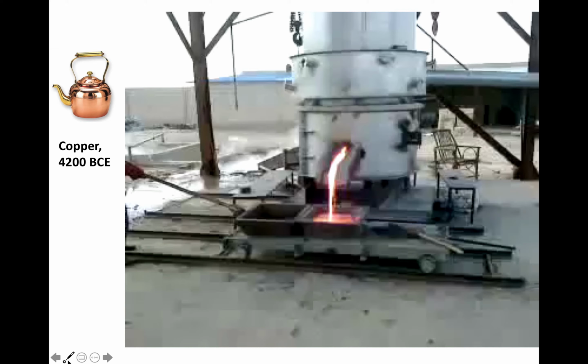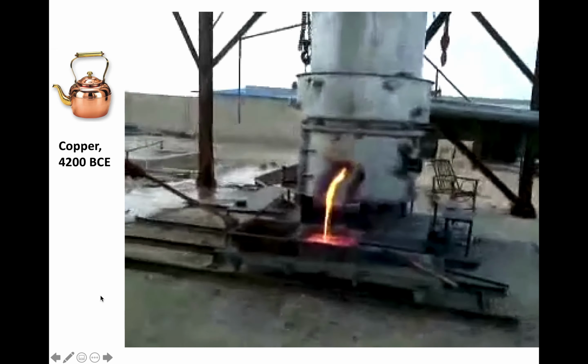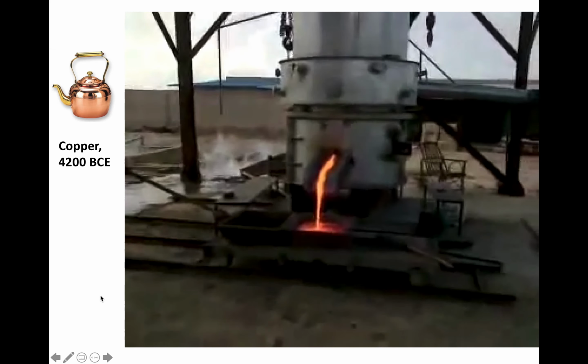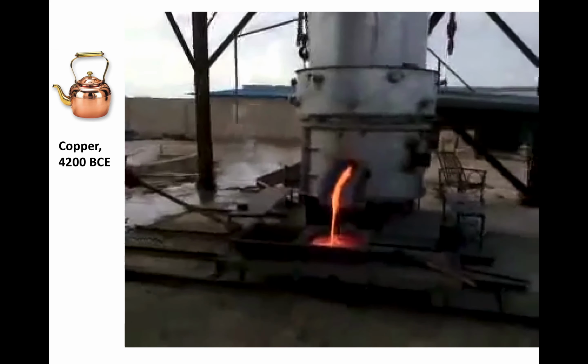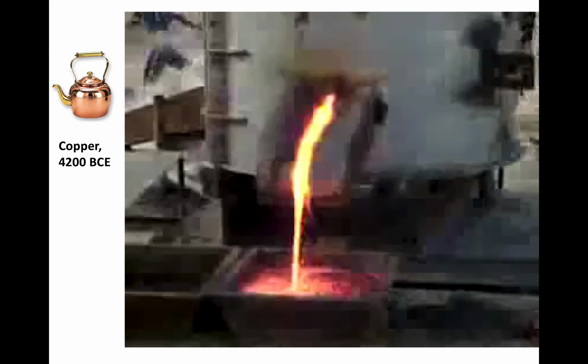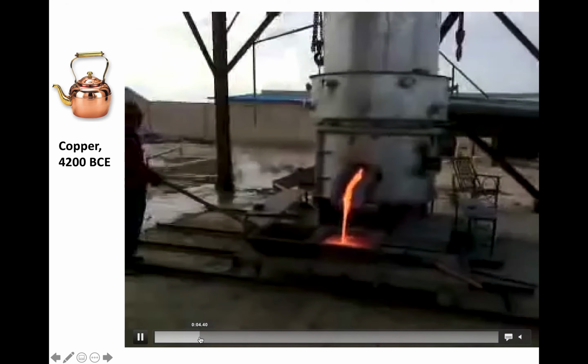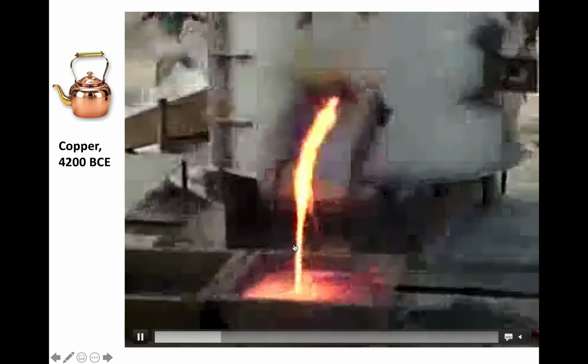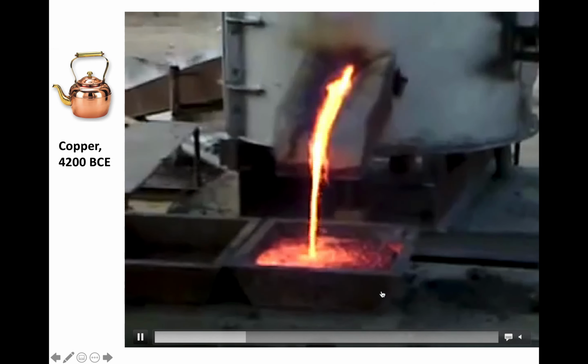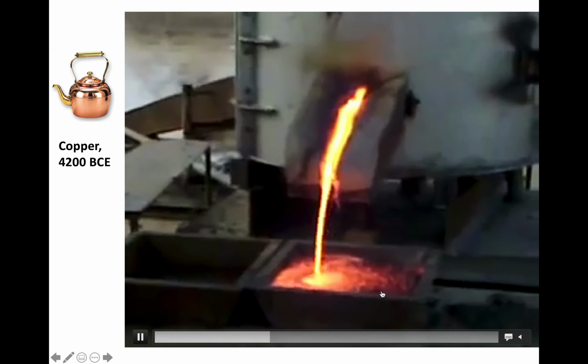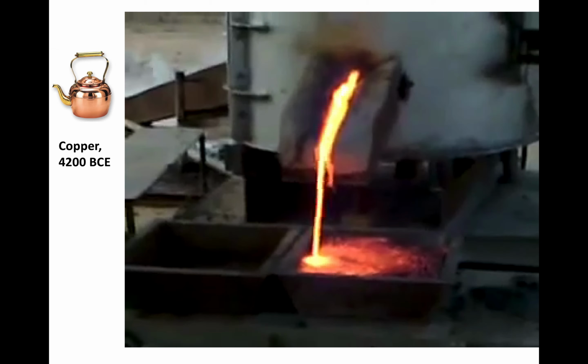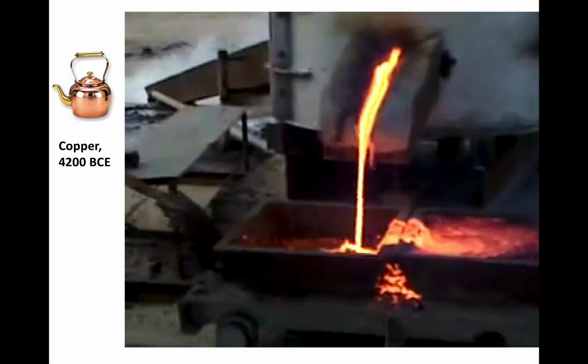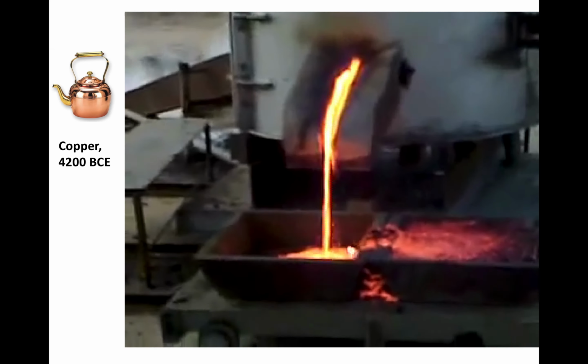So this is a video, and I'll play it just to show you what that blister copper looks like coming out of the bottom of a converter furnace here. So that is blister copper liquid, 98 to 99% pure copper, and it's being poured into a mold. So this is a mold here that will not melt at those high temperatures. And that blister copper liquid is being poured out of the furnace, and then they'll move that mold to the right, lose a little bit of copper, but they pick that up.